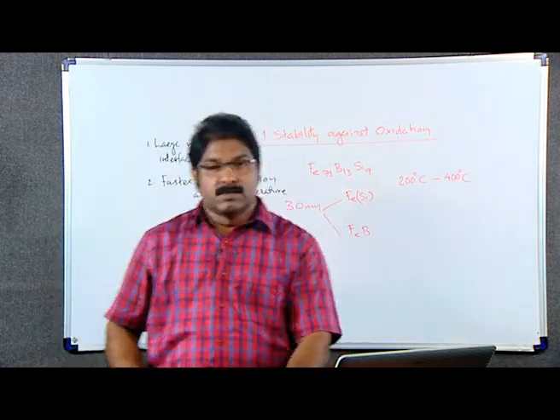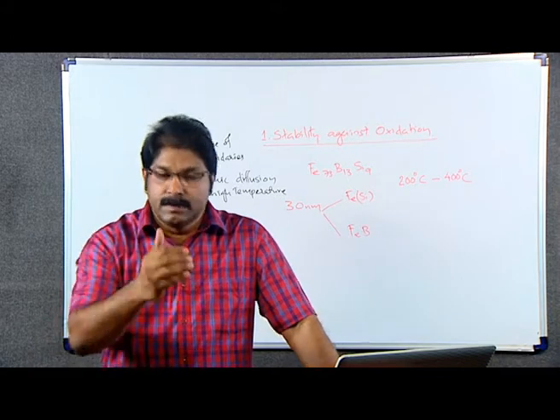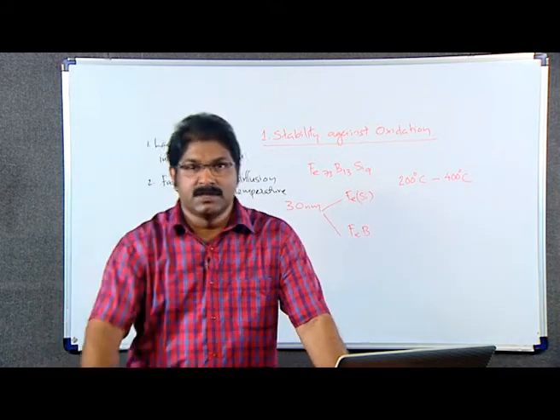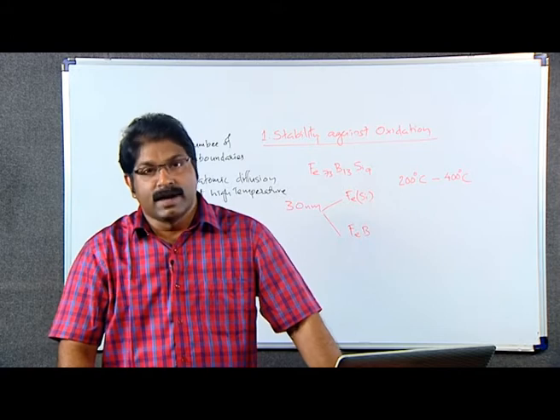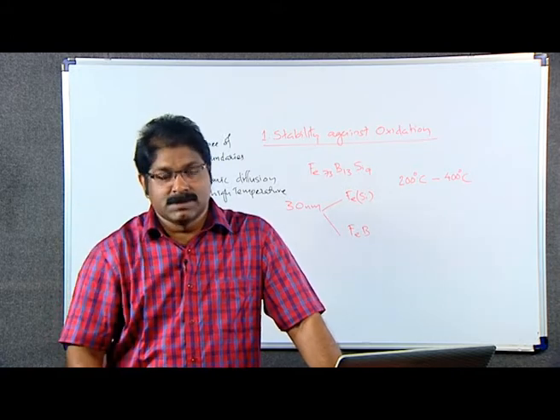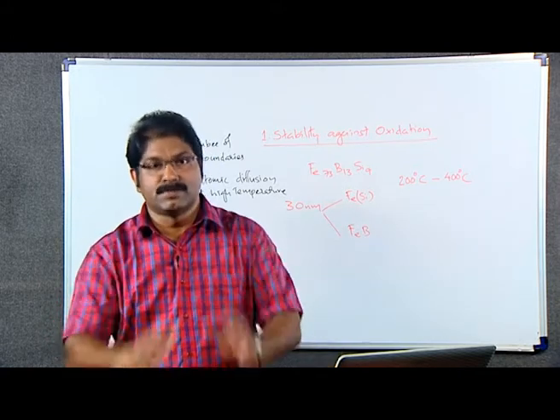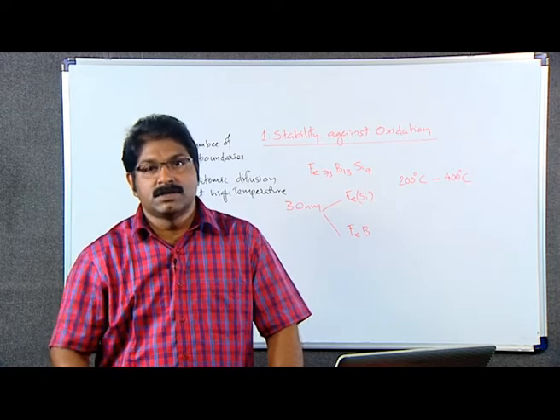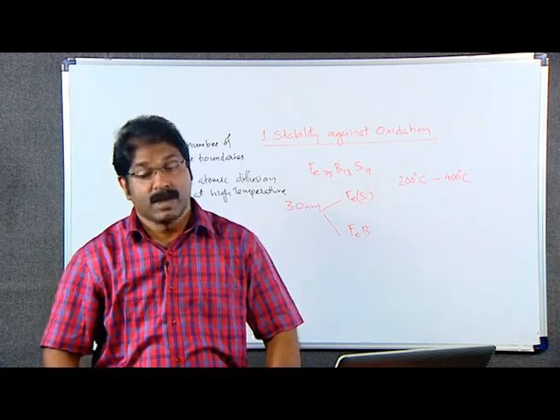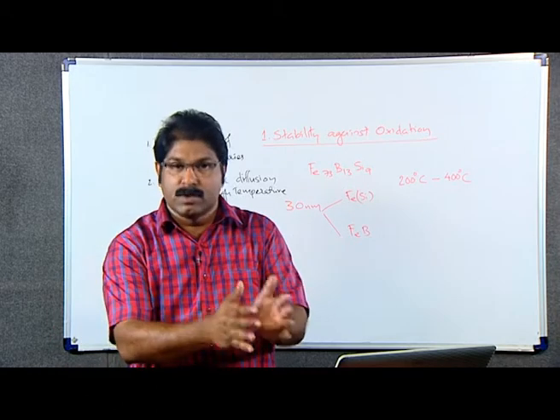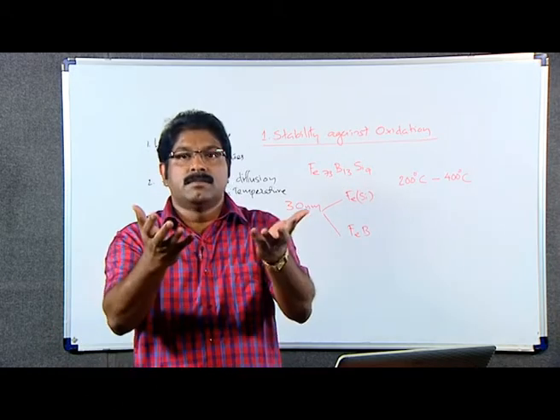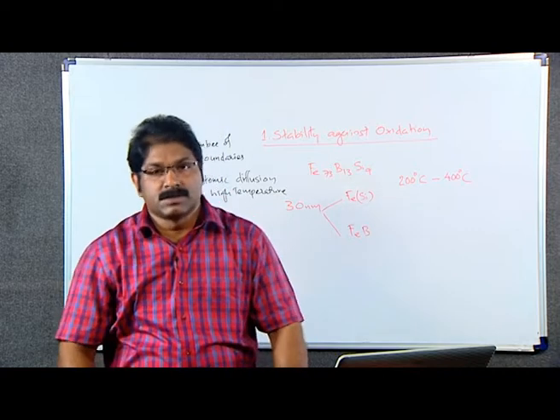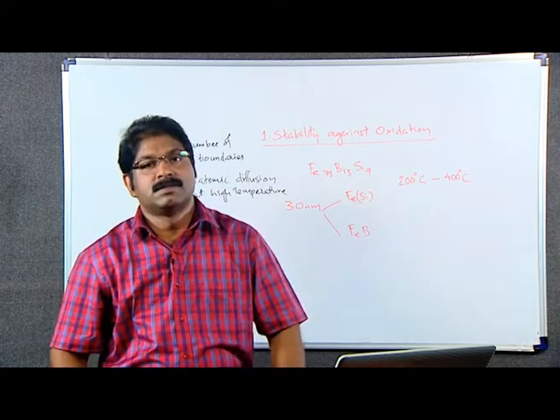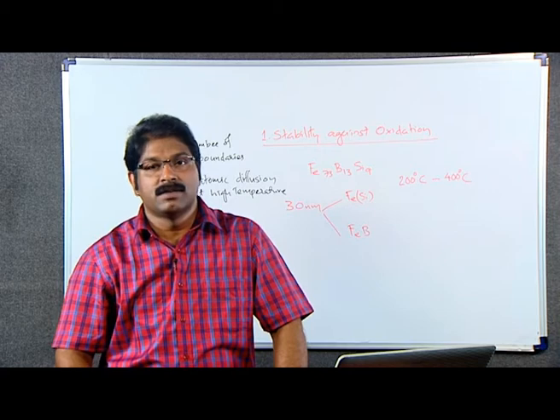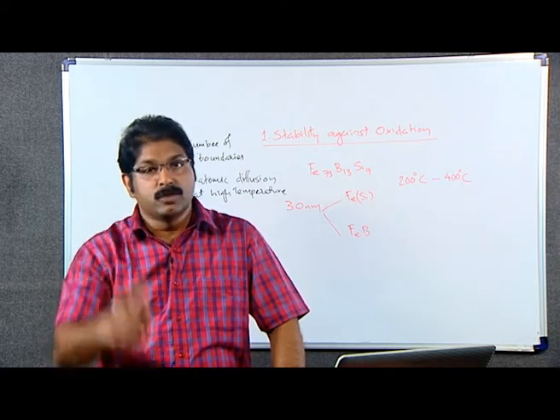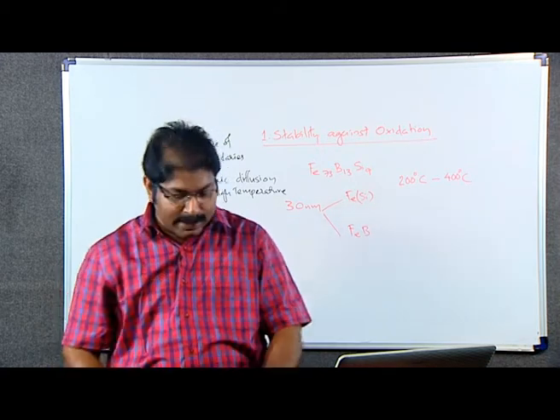Let us see what this means. In the material which we have just considered, that is Fe73 B13 silicon 9, the silicon atoms segregate to the interface boundaries and afterwards they diffuse to the surface. At first they segregate to the interface boundaries, thereafter they come to the top surface. At the surface, this silicon interacts with oxygen in the air and forms a protective layer of silicon dioxide.